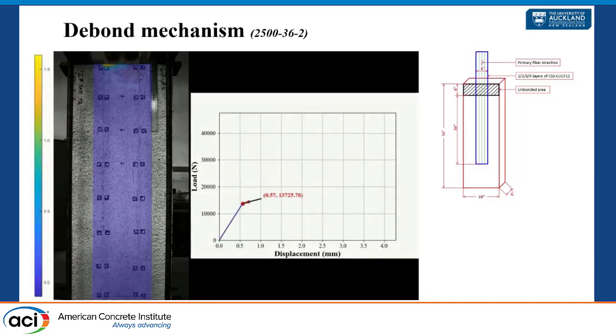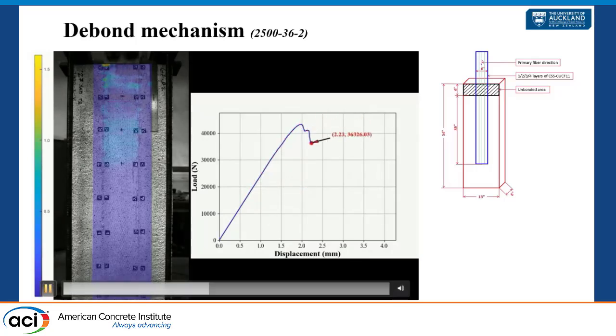We can say that in the initial stage, it's completely elastic up to a certain point when the FRP ties start to debond. And we can also say that the strain-active bond zone moves from the loaded end down toward the free end. The strain also has increased.